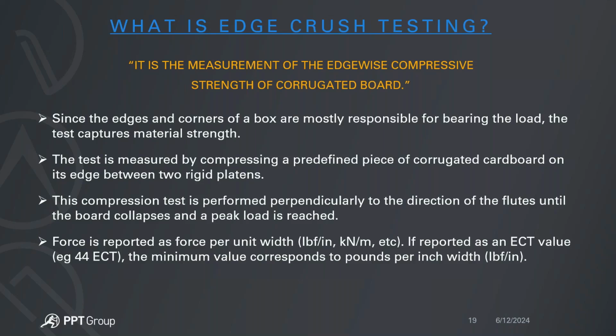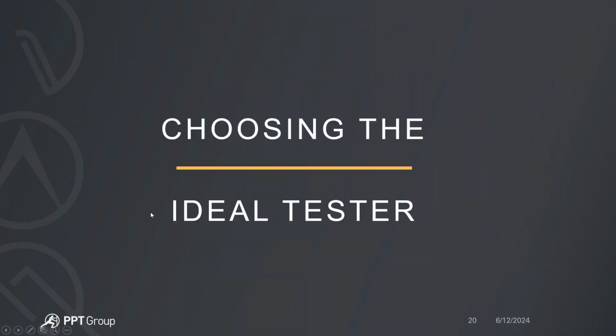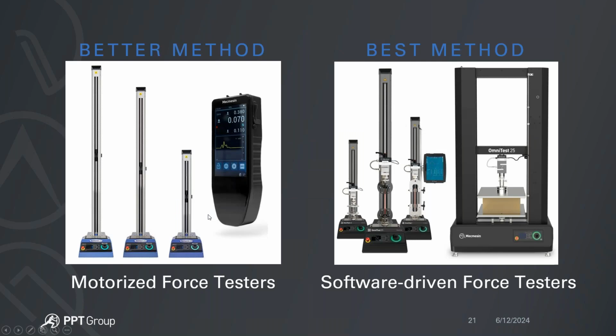So you'll find probably 2-inch wide by 6-inch long samples that are usually put between two base plates or just a slotted base, and then a compression platen is lowered, touches the sample, and compresses to a known deflection or to the point of failure, and then you measure the ECT, or the actual maximum force it takes to collapse the sample. Once again, the ideal testers for ECT are either motorized force test stands for very simple test applications, or software-driven force testers to perform the actual calculations that will yield the force per sample width results that you're looking for.